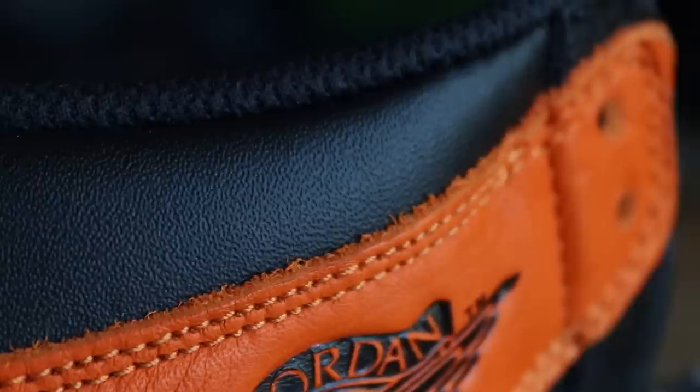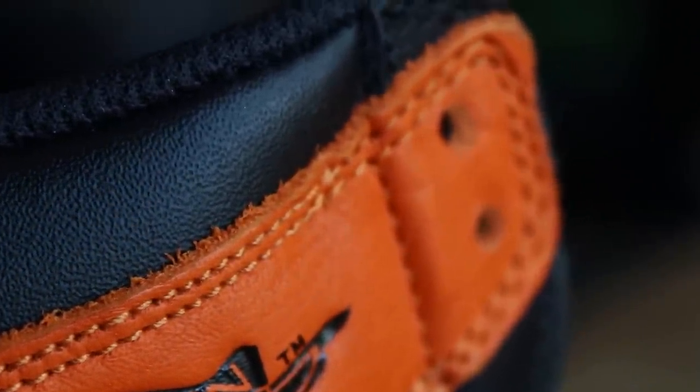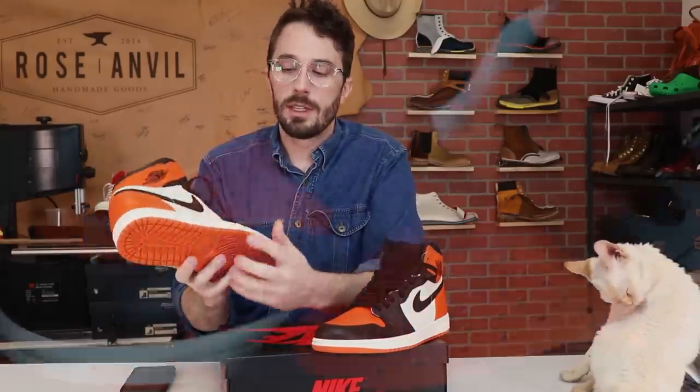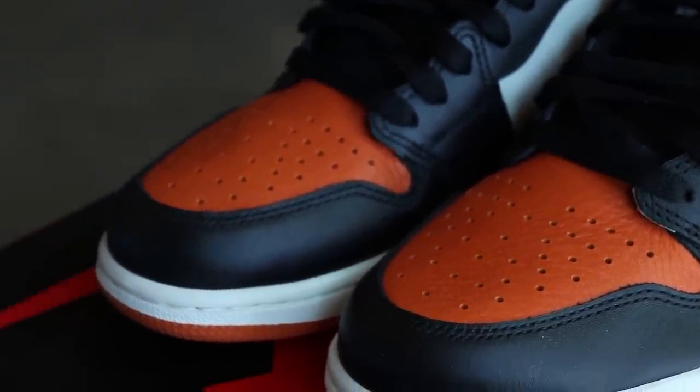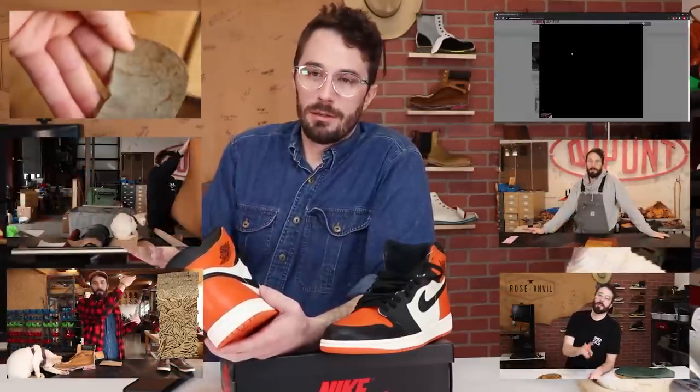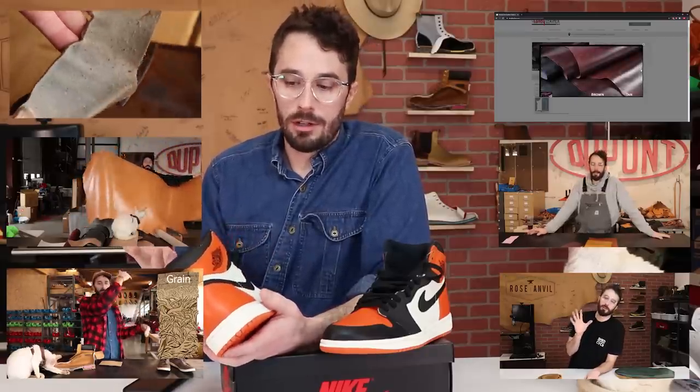You can see this raw edge and there's a lot of really loose fibers on it. That's not always a sign of bad leather but it's not a sign of great leather either. Usually you want to see a really tight packed grain pattern, and these little flyaways are not usually present in a high quality leather. But this leather is tumbled — tumbling takes a firm leather, throws it in a giant dryer without heat, softens those fibers up, and gives it that pebbled look. This leather is also dyed all the way through, so it's really hard to see if it's chrome tanned or vegetable tanned. I'll put the leather basics video playlist in the description so you can educate yourself on the basics of leather quality.